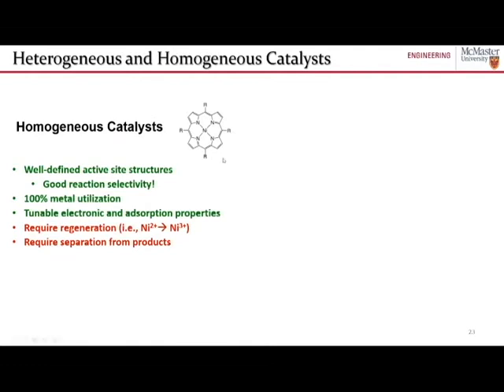In principle, you can also get 100% metal utilization because every nickel site is, in principle, accessible to the reacting species within your mixture. This is not the case in something like a nanoparticle where you've got millions of metal atoms and it's only those surface metal atoms that are accessible to the reactants. Therefore, your utilization is much lower than 100%. When I'm talking about metal utilization, the big driver there is cost. If you're going to spend money putting metal into these catalysts, you might as well use all of the atoms of metal that you put in there.